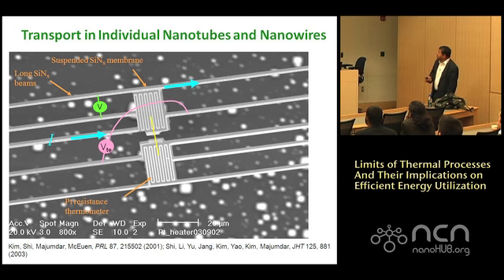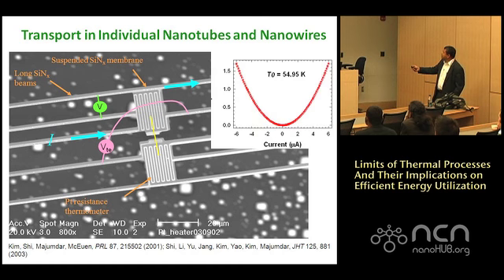And we developed this technique, most of you probably know this, if not, I'll go very quickly, of measuring the thermal conductivity of single individual nanowires. These are 2 suspended, this is a classic heat conduction experiment. 2 heaters, 2 temperature reservoirs, one higher temperature, one lower temperature. You pass current through this, you electrically heat this, and you can get I-squared behavior of this for current and temperature. And there's a 4-point probe, so you can use it as a heater and a temperature sensor.